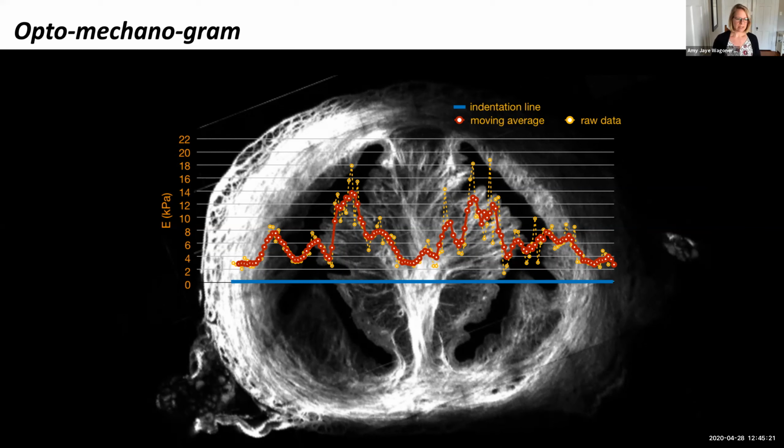You can't see GAGs. The GAGs are the glycosaminoglycans, by the way. Those are the molecules that work well in compression, that resist compressive forces pretty well. So I don't think that you can image those without using a stain. And so AFM would not allow you to image the GAG molecules, to my knowledge. You would have to use something that would stain so that you could see in fluorescence or other optical modality, or you could use electron microscopy and use a stain, but I don't think you could see them with AFM.